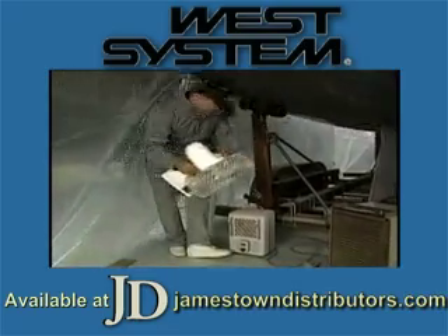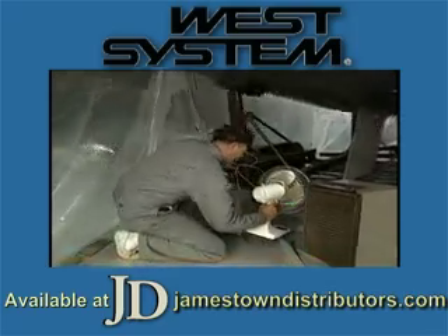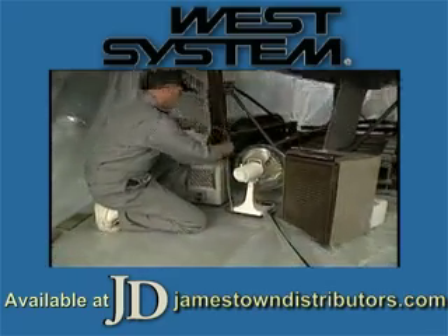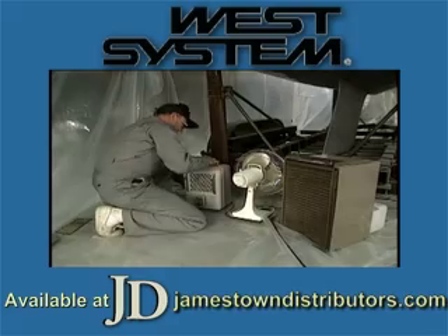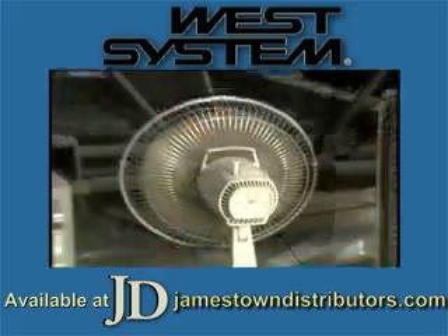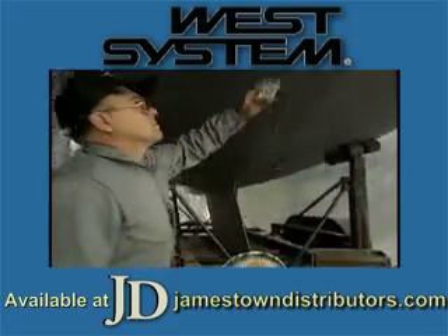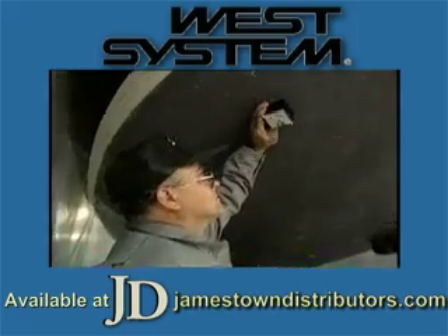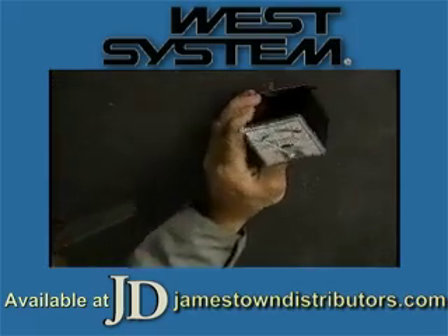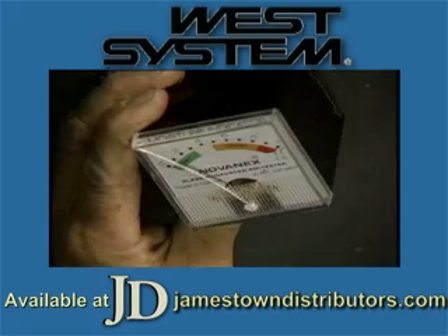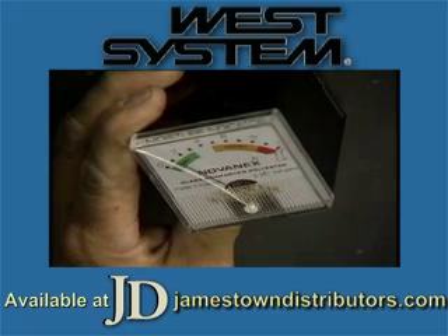Fans, heaters, and dehumidifiers promote aggressive drying of the laminate. That could reduce drying time from months to weeks. The goal is to get the hull to a point where drying ceases, or when you get consistently low moisture meter readings below 3%. Now you can begin the repair procedure.